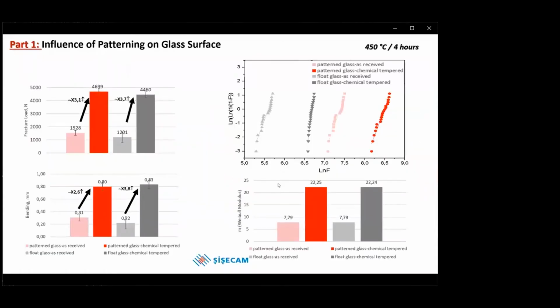In this slide, ring test results and Weibull modulus are given. According to the results, after the chemical tempering process, the fracture load value of the SGC pattern sample increased up to 3 times, while the fracture load values of the float glass sample increased up to 3.7 times. Considering the amount of bending of the glasses during the ring test, it was determined that the increase in the bending values of the patterned glass was lower compared to the float glass. The Weibull modulus of the SGC pattern and float glass samples increased from 7.8 to 22 after the chemical tempering process.